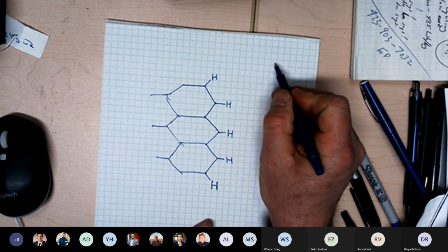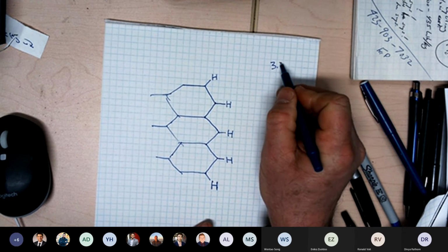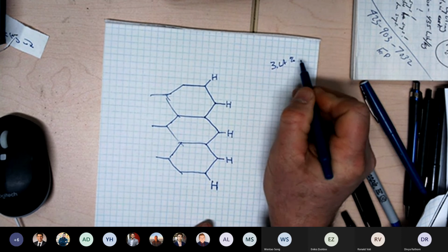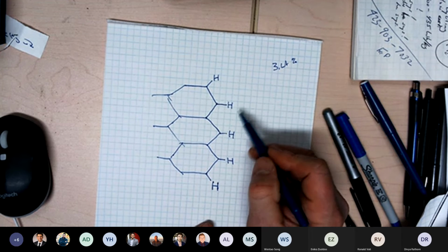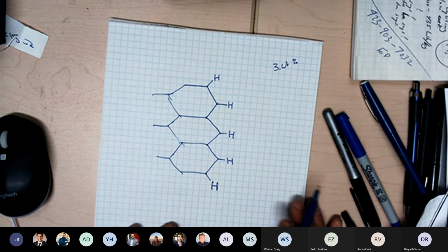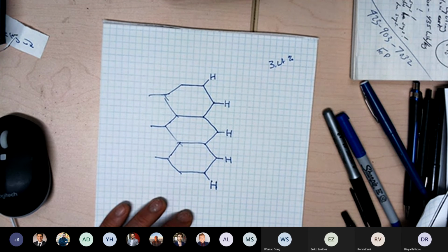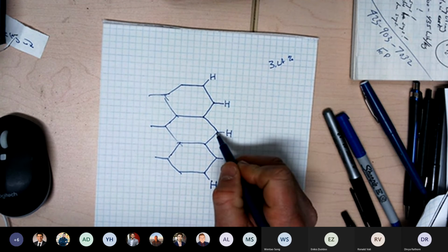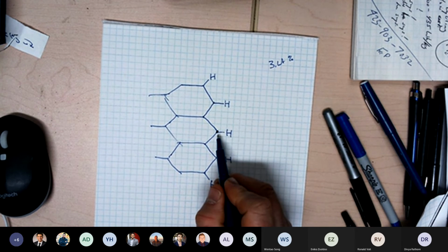Like those numbers I was showing you were in weight percent. So it's like three weight percent. And hydrogen is 1/12 the atomic mass of carbon. So 3 weight percent is a large atomic percent of hydrogen. So the idea is, this carbon that you have here is an sp2 bonded carbon.